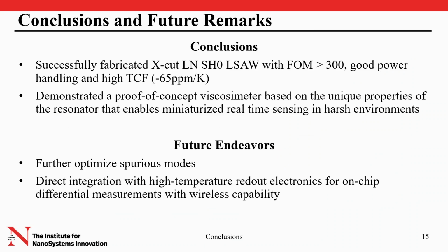To conclude, we successfully fabricated very high performance leaky SAWs that leverage the shear horizontal mode on XCUT lithium niobate with good power handling and a very high temperature coefficient of frequency. We employed this unique mode shape of vibration to realize a proof of concept viscometer for real-time in situ sensing in harsh environments. However, the work is not done. Of course, we need to further optimize the spurious modes, either employing Bragg reflectors for the lateral spurious modes and apodization of the fingers for the transverse spurious modes, as well as developing high temperature readout electronics for on-chip differential measurements with wireless capability.